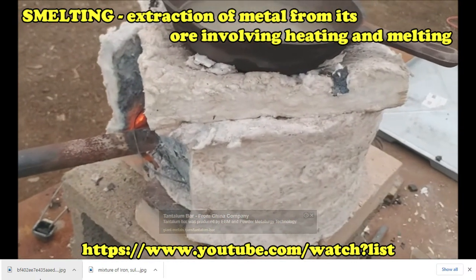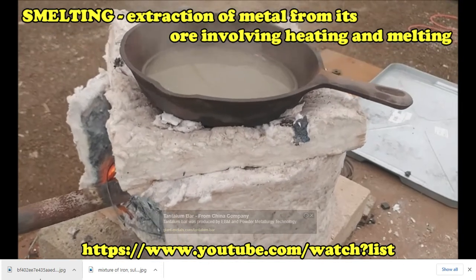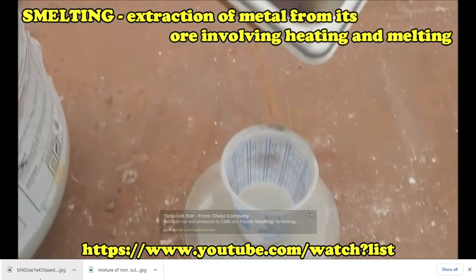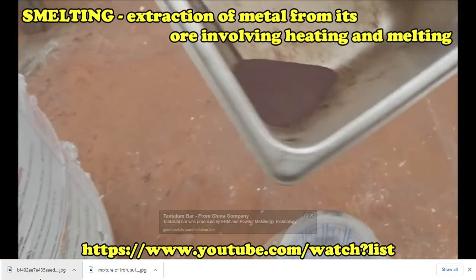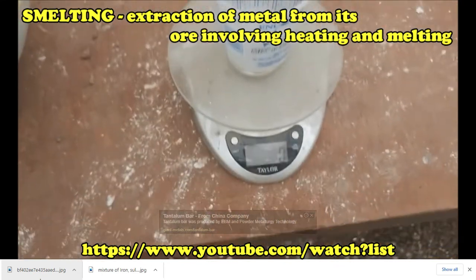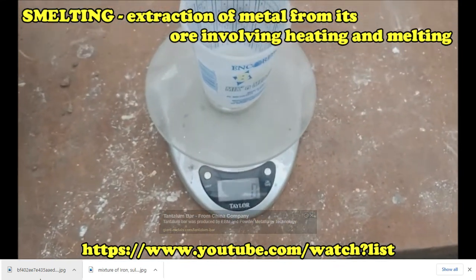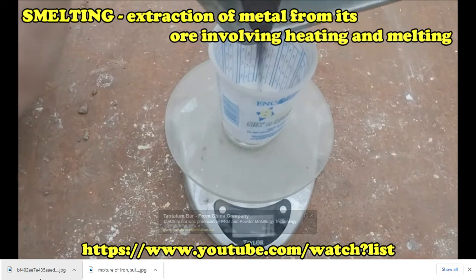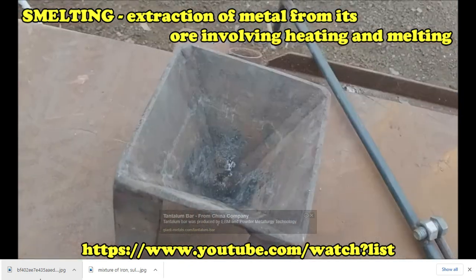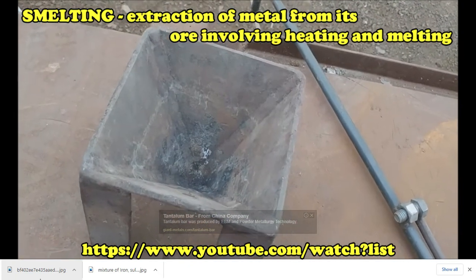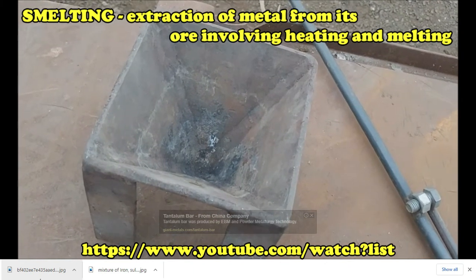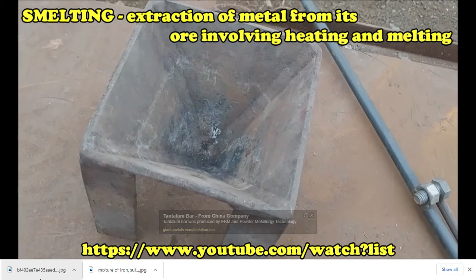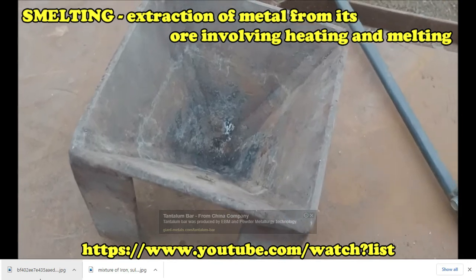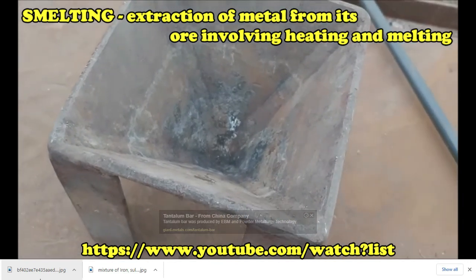Got some Kaowool wrapped into a little cylinder there with a top on it. And here's our little scale. We've got our oxides now, our roasted sulfides. Figure out how much they weigh here. And when you pour the charge in there, the gold is the heaviest, so it goes to the bottom and all the slag floats on top, and we should get a little gold button at the bottom there.